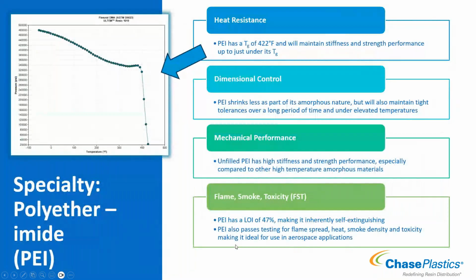All right, so some performance features - high temperature performance. As you can see with the high temperature needed to process it, it has really good heat resistance. Its TG is 217C or about 422F, and it maintains a lot of that stiffness performance until that temperature. If you look at the chart, it loses a little bit, but really it holds on to most of its flex modulus performance out until right about its TG, and then it loses its performance. Good continuous use performance to about 190-200 degrees C. So great temperature performance there.